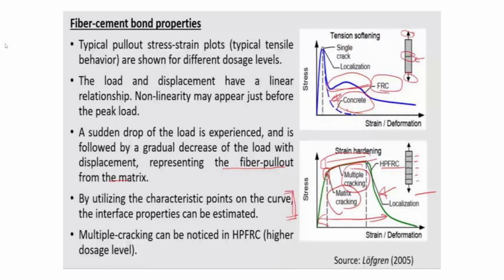Fiber cement bond properties. Typical pull-out stress strain plots, showing typical tensile behavior, are shown for different dosage levels. The load and displacement have a linear relationship. Non-linearity may appear just before the peak load. A sudden drop of the load is experienced, followed by a gradual decrease of the load with displacement, representing the fiber pullout from the matrix. By utilizing the characteristic points on the curve, the interface properties can be estimated.